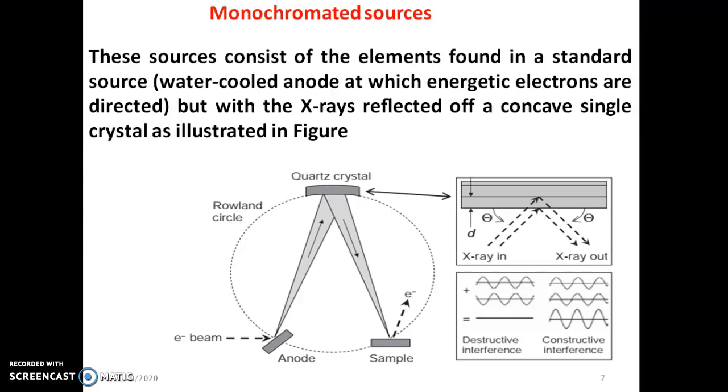And this quartz crystal, when the X-ray from the X-ray tube falls on the quartz crystal, depending upon the Bragg's conditions, the rays are either coming out or get suppressed. So a particular wavelength, depending upon the geometry of anode and quartz crystal, the particular theta and particular wavelength X-rays are emitted out and other wavelengths get suppressed by the destructive and constructive interference condition. Then again, the quartz crystals are made with a little bit of concave curvature so that the X-rays get more focused